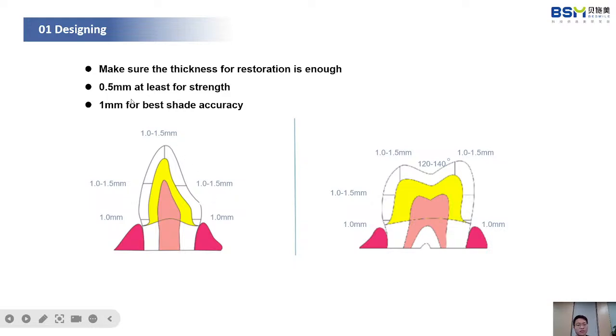But actually, we recommend 1 millimeter. The reason is, usually we can get the best shade accuracy when the thickness is 1 millimeter. Because when we do R&D and test the shade, we will mill a 1 millimeter disc to test the shade accuracy. So when we design the crown and the thickness is around 1 millimeter, we can get a more accurate shade. And we know for some cases 1 millimeter is too much.